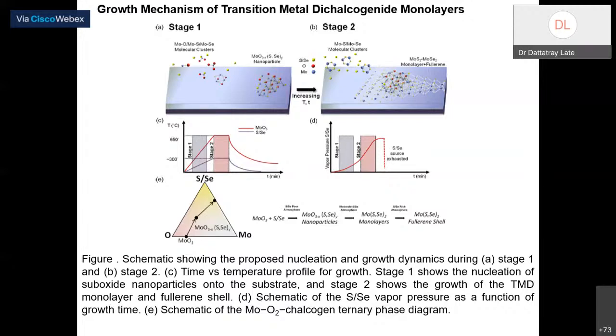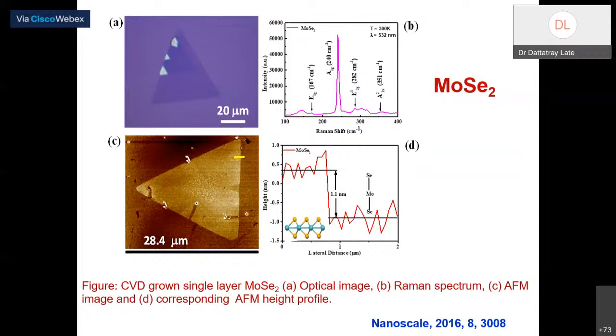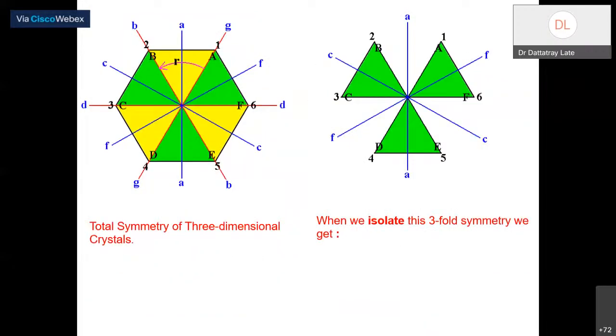Thickness can be tuned depending upon how long your reaction is going on. So this is again an optical image and AFM image of that MoSe2 layer, which I have grown just by chemical vapor deposition. Of course, again here you can use Raman spectroscopy and atomic force microscopy to characterize the different layers.